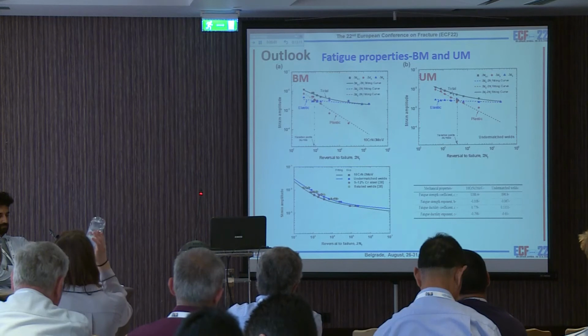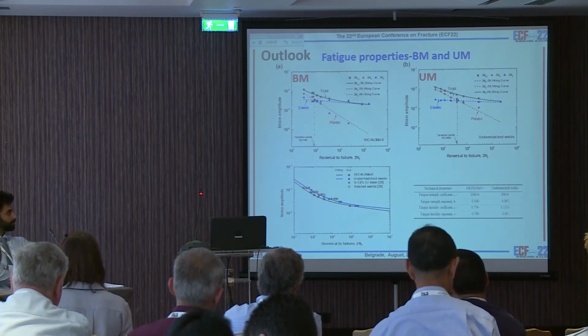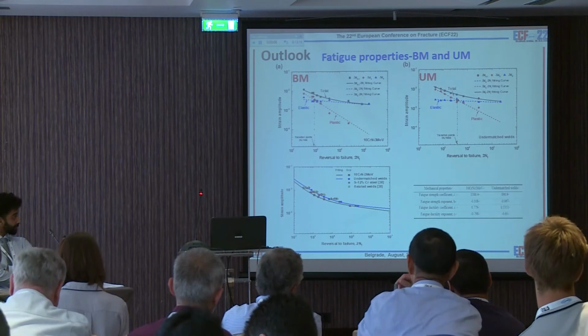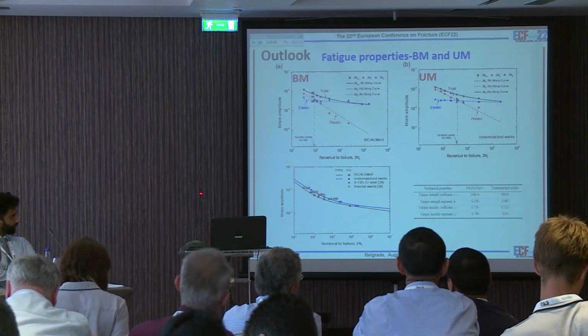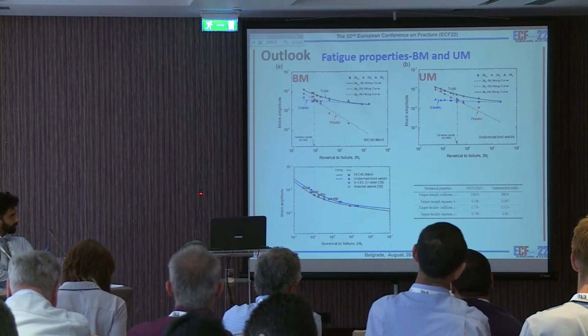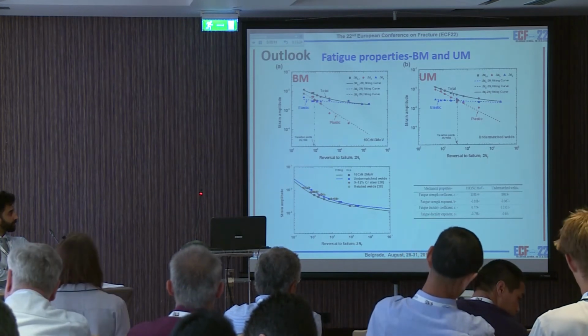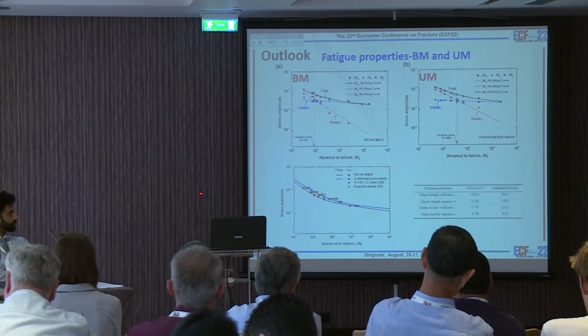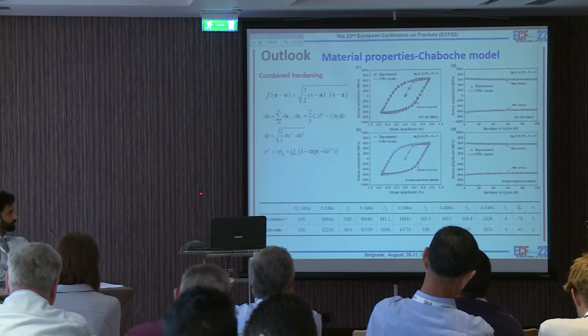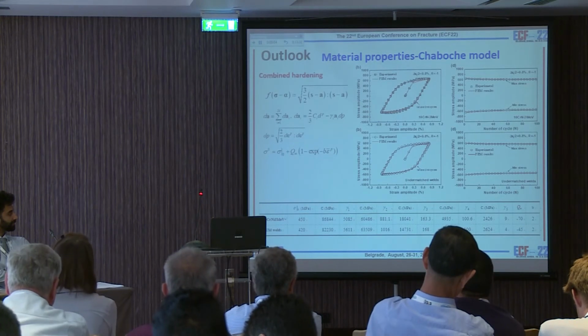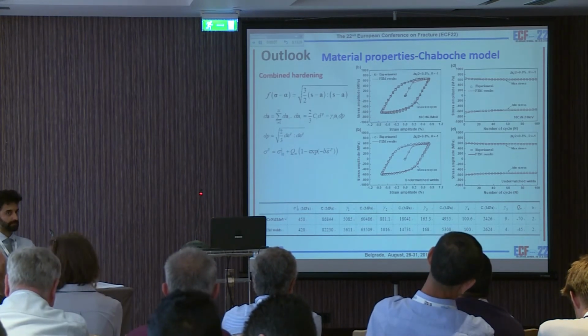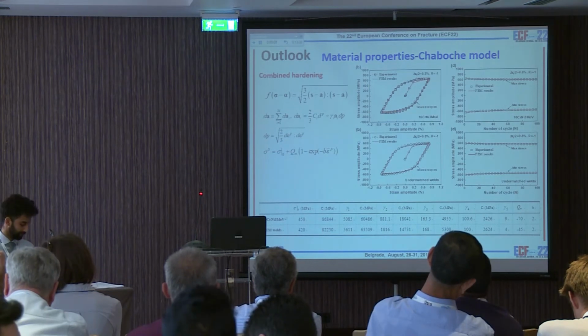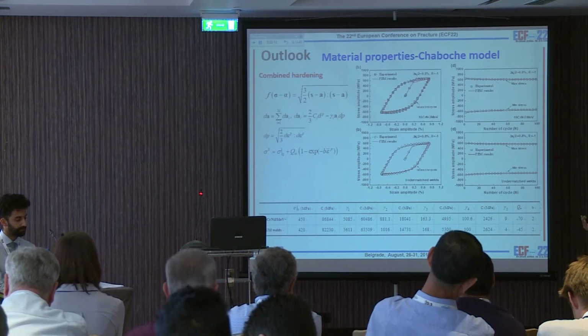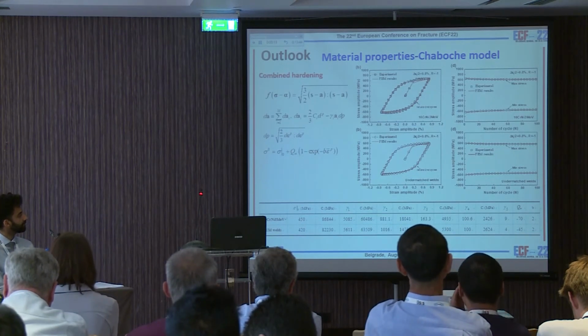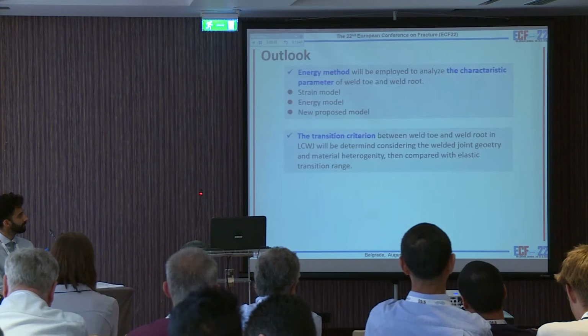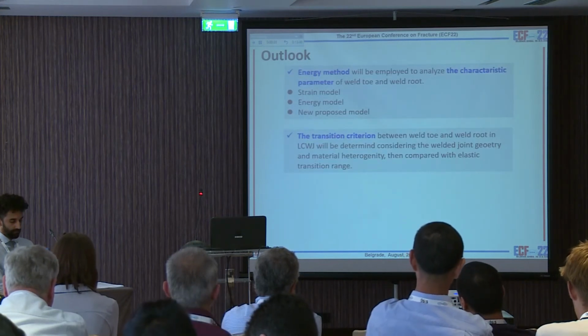So the next step, I want to use the masing hysteresis curve between the base metal and undermatched metal to predict the welded toe and welded root characterized parameter. And we also used the Chaboche model to simulate the welded toe or welded root parameter under the elastic and plastic range.